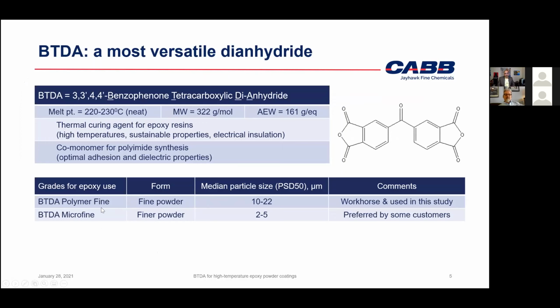So the workhorse for the industry is what we call BTDA polymer fine powder, that has a median particle size of 10 to 22 microns. And that is the grade we did use in this study as well. There are some customers, some applications that find it is better to have a finer particle size. And for them, we do produce what we call BTDA microfine, which takes down the median particle size to 2 to 5 microns. Kevin, anything you want to add?